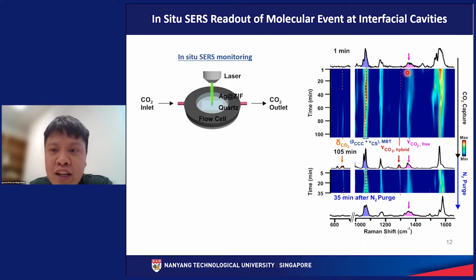So initially, we started out with the characteristic SERS feature of our methyl benzene thiol or MBT. So this is a C-S stretching, whereas this is a C-H vibrational mode. So what is more interesting is over here, whereby we can see the CO2 stretching mode of free carbon dioxide molecule. So I will go through what is free and hybrid in our subsequent slides. So as we can see, with continuous CO2 absorption or capture, there is a continuous shift and evolution of our SERS spectrum with time.